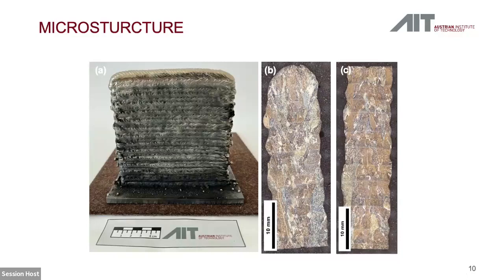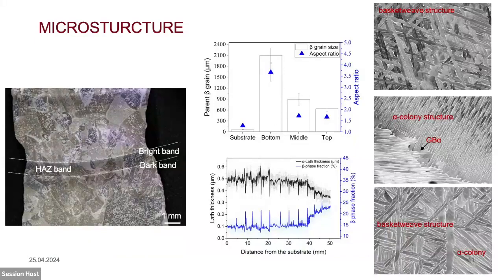Some more details of the microstructure. The layer formation that I've shown before has been analyzed. Let's start with the layers that are below here. We have on the one hand a variation of the lath shape, and on the other hand, a variation of the beta phase fraction. That is very local because the solidification conditions are different there. The second part is the grain structure that you can see here in comparison to the substrate. Of course, the substrate is a wrought material with a very fine grain structure. And what we see here is that throughout the build height, the primary grain structure gets slightly refined. That is an effect of heating up the material and thereby affecting the thermal gradient.